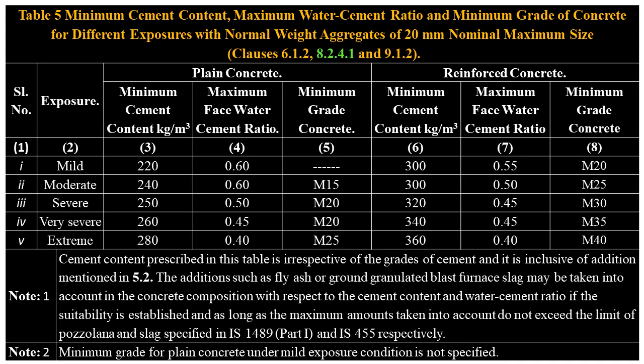Plain concrete, minimum cement content 260 kilograms per cubic meter. Maximum free water to cement ratio, 0.45, grade of concrete, M20. And for reinforced concrete, minimum cement content 340 kilograms per cubic meter. Maximum free water to cement ratio, 0.45, grade of concrete, M35. Serial number 4. Exposure, very severe.